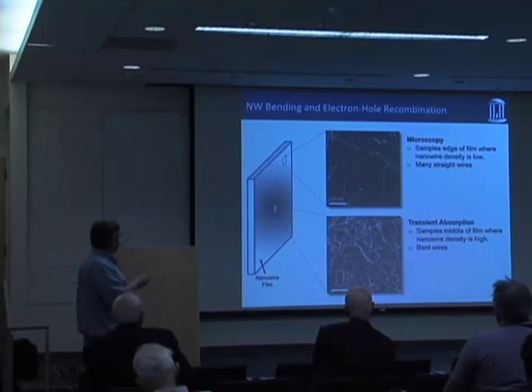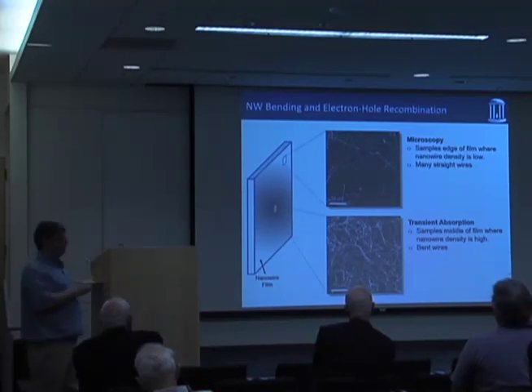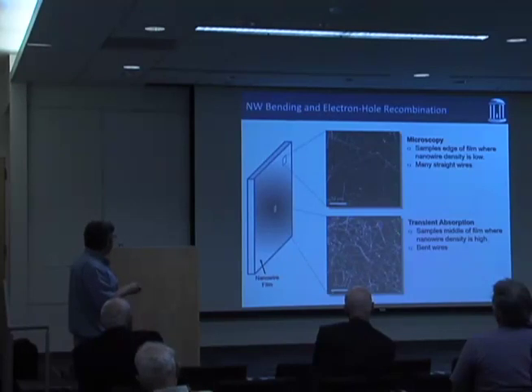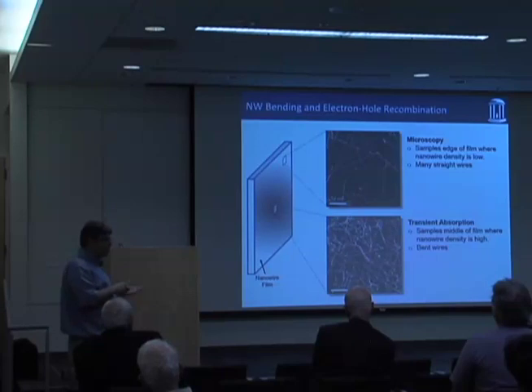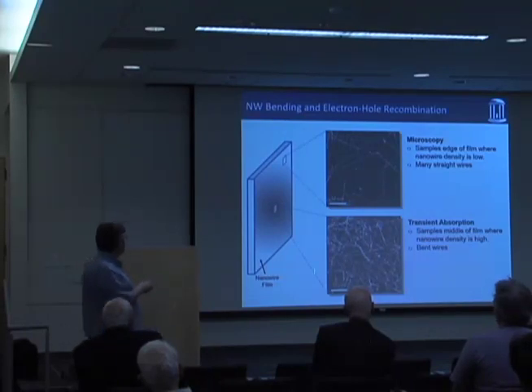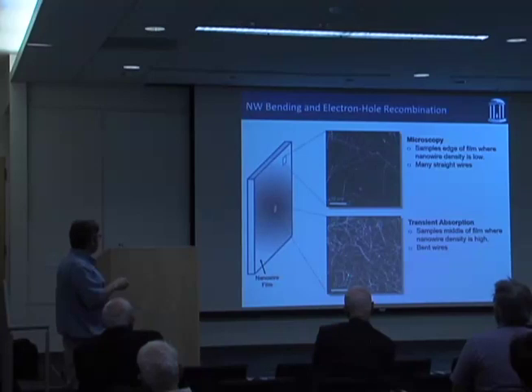And this is what the SEM of those wires looked like. And one thing you can tell, just comparing these two, is that here all the nanowires, or a lot of them, are straight, just like you would expect them to be. And down here it looks more like a bowl of spaghetti. There are some straight ones, a lot of curved ones, and so on. And so we started to think, well, does that curvature have something to do with the differences that we're observing in the two techniques? Because in the transient absorption, you're averaging over all of this stuff, but in the microscopy, you're selectively sampling more or less just the straight wires.